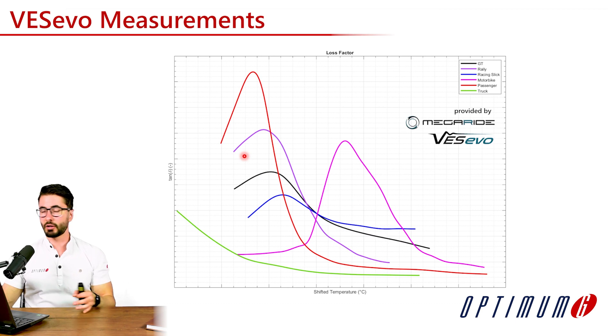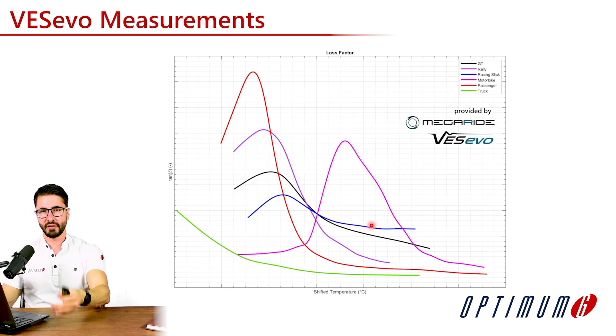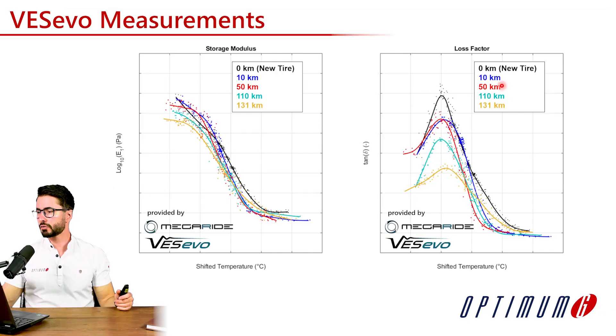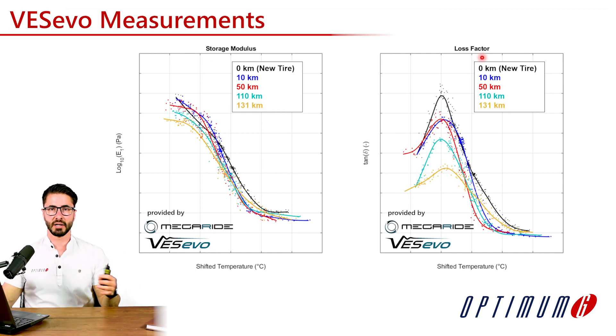We could also look at the loss factor. Comparing a Racing Slick, we can see that at high temperatures it will have a higher loss factor or more hysteresis, helping the hysteretic grip, compared to a passenger tire. Besides that, we can see what happens with the tires as we wear them at the track — for example, comparing a brand new tire with a tire with over 100 kilometers, to see how this is changing the storage modulus and the loss factor, and to try and make sense of what the tire is displaying at the track.